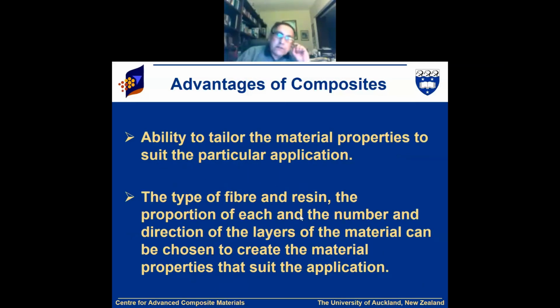Ability to tailor the material properties. Like we know the extruded rods have some properties in the extrusion direction and different properties in the transverse direction. But when we use a metallic material, we really cannot control those properties, and most of the time we assume them as isotropic material. That means properties are the same in every direction, independent of the direction. That isotropy can sometimes waste material, because you have to put material in a direction where you don't need that sort of reinforcement. So that is one advantage: we can put the fibers or the reinforcement in the suitable or preferred direction. That creates problems also. I'll come to that.